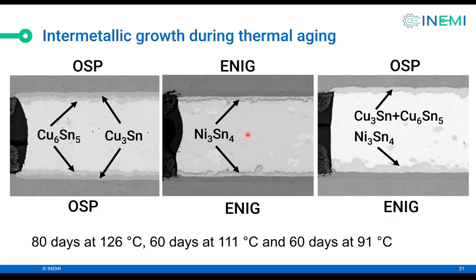Before I go there, let me just show you what happens if we do just thermal aging. If you do thermal aging on OSP soldered with this alloy, you get Cu6Sn5, you get Cu3Sn. So this is an intermetallic. If you have ENIG, which is mostly nickel, you get Ni3Sn4. You can see the thickness of Ni3Sn4. And then the third case is OSP on the top, ENIG on the bottom. On the top, we get Cu6Sn5, and on the bottom, you get Ni3Sn4. So nothing surprising over here, right?